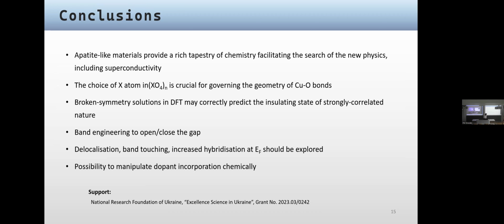And so, just picking this up, this composition that you investigated, is it stoichiometric? Yeah, so it's stoichiometric. In the experiment, yes. Because then it's very unusual. If you have a stoichiometric system and you apply some U in the plus U scheme, then I think you always get a gap. But there people couldn't, and it was also one of the points that led to the interest initially. Of course everyone applied U from the beginning, but initially everyone got the metallic state. Me too, I repeated the calculations as well, and same. And this band that crosses the Fermi level, it's a copper band. It's copper 3d with hybridization from the neighboring oxygen orbitals.